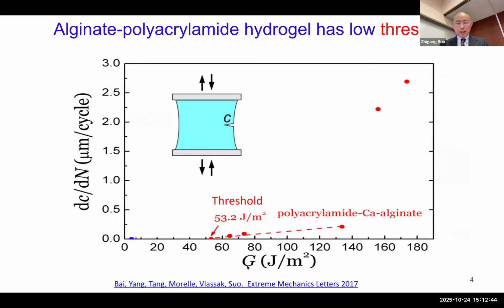So again, this is a number, joule per meter squared. This is called energy release rate. As I mentioned, the toughness itself is 1,000 joule per meter squared. In a later version, we actually demonstrated more than 1,000, 10,000 joule per meter squared for the same material. Now, if you do cyclic loading, this G is now the amplitude of the cyclic loading.